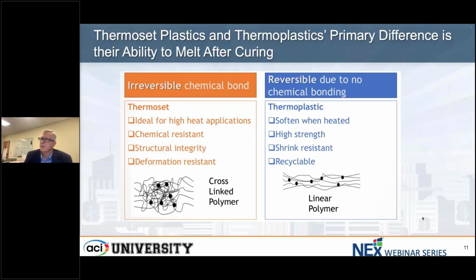So in a thermoset, you're creating an irreversible chemical bond. So you have these polymers, which are shown in the black squiggle, and then you cross-link it, and the cross-link is shown with the black dot. And that creates a cross-linked polymer. And it's ideal for high heat applications, for chemical resistance applications, for when you need structural integrity, and when you don't want things to deform.